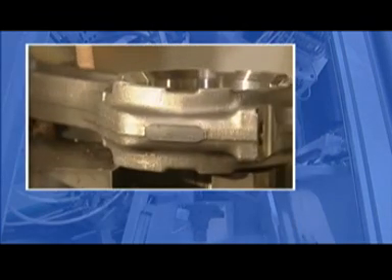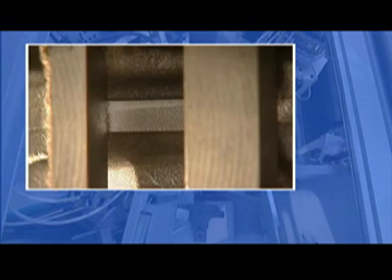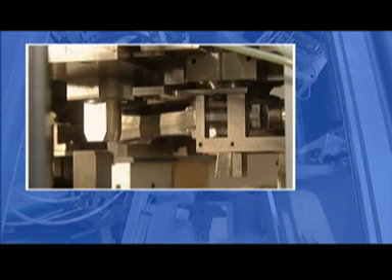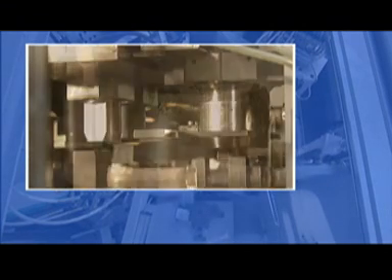The next step in the process is the actual cracking. A hydraulic system pulls the two halves apart with a force of 40 metric tons. By cracking, we can reduce additional operations, such as machining location holes and installing pins to force the two halves into position.